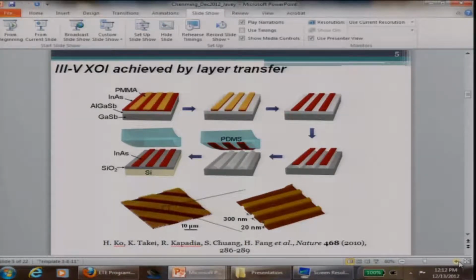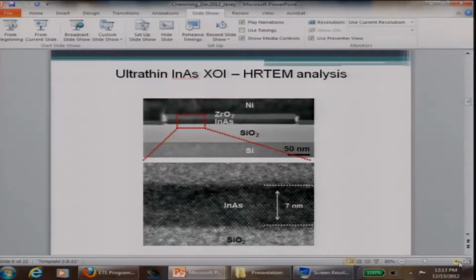And for the III-V work, what we do is we use a layer transfer process to transfer very thin layers of III-V of our material of choice onto a silicon oxide substrate. And the way we do it briefly is that we grow our active material, in this case indium arsenide, on a III-V substrate with a sacrificial layer, which is aluminum gallium antimonide. We pattern etch indium arsenide. We then selectively etch the sacrificial layer. And in this case, we just pick these layers up, and we transfer them onto a silicon oxide substrate. And the resulting atomic force microscope images look something like this. The yellow lines are indium arsenide. The brown is your SiO2 background. So you can now transfer very thin layers of, in this case, indium arsenide onto silicon oxide.